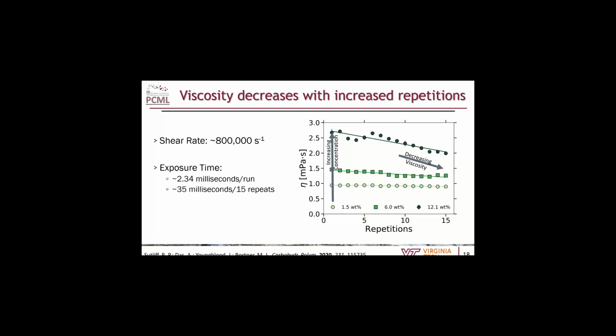I did some quick calculations. The time each cellulose nanocrystal was exposed to these shear rates was about 2.34 milliseconds per run, or 35 milliseconds for the duration of what's on this graph, which really isn't much time to be at these shear rates when you're talking about injection molding and other processes that are going to be pumping these through machines for long periods of time.